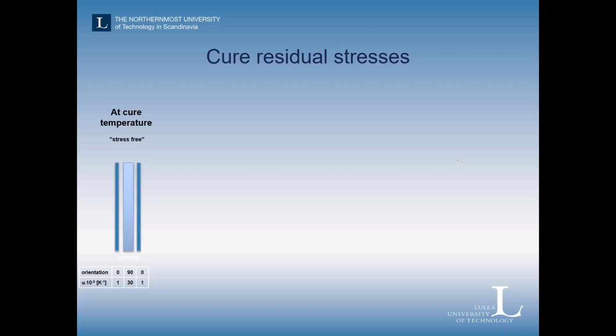viewing the edge of a laminate, we have the fibers in the outer layers in the 0 degree direction, and the middle layer in the 90 degree direction. There's a big difference in thermal expansion coefficient for these different layers. So what happens when we cool it to room temperature?